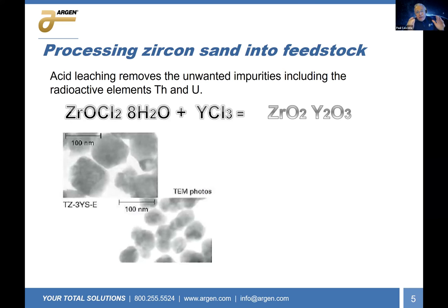This process is a very intense commercially large chemical process where the sand actually gets dissolved in hydrochloric acid. So it's extremely aggressive and it has to be done in very, very large quantities. A typical batch of zirconia is 5 metric tons. It's very, very large. And through this dissolution process in the acid, we eliminate the thoria and the uranium, as well as the silica and the majority of the other elements. Now, we form this soup of zirconium chloride, and now you have a choice. And the processing for dental zirconia begins at this slurry stage. This big oatmeal thing will now determine what you want out of it.